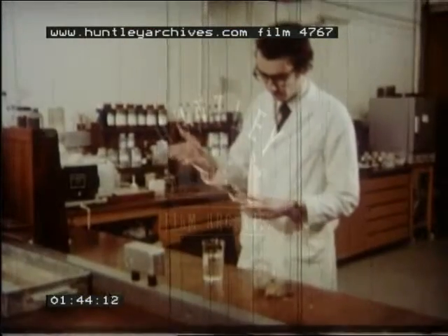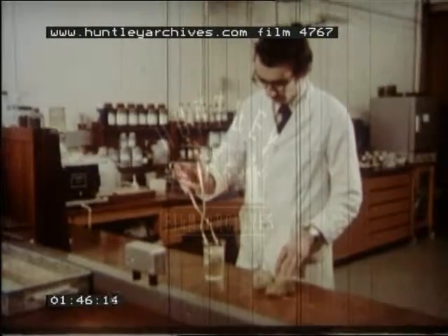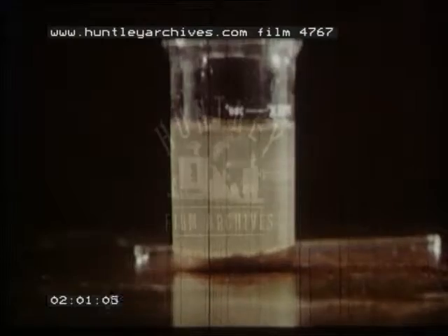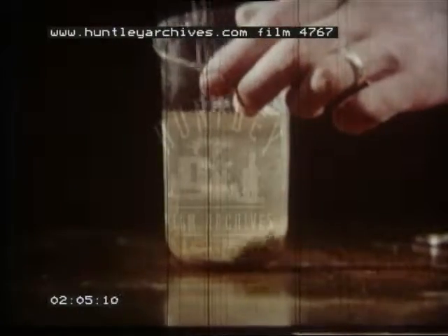Although chemical attack on stone leads to the formation of salts and thus contributes to crystallization damage, it is only in special cases that chemical attack can be said to be the sole reason for decay. One such case is the decay of calcareous sandstone, in which the acidic rainwater, shown here with additional acid, dissolves the small amount of binding matrix and thus loosens a large number of silica grains.